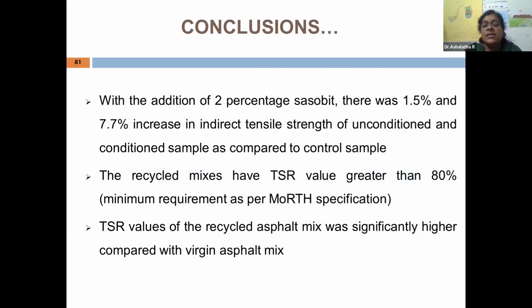And the recycled mixes have TSR value greater than 80%, greater than the minimum as per the MoRTH specification. And the TSR values of recycled asphalt mix were significantly higher compared with virgin asphalt mix.